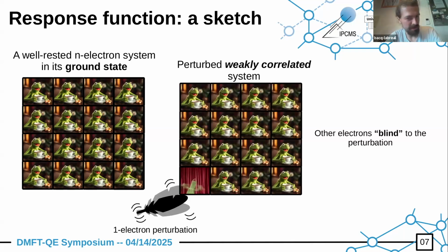So ARPES, for instance, would be a one electron perturbation. And if your system is weakly correlated, well, you will perturb one electron. For instance, you would create a photoelectron from one of them, when all the others would basically not see anything, right? Because they would be weakly correlated. So this is as if you would basically probe a pure piece of copper or something. In this case, well, DFT could be quite good because you could use the one electron states from the Kohn-Sham system, and probably you would get some good estimate, let's say.